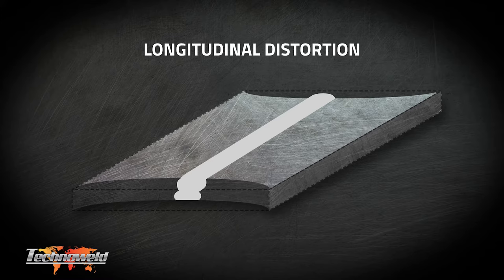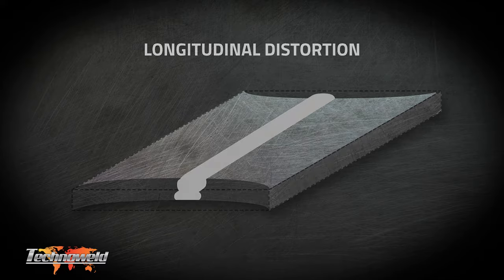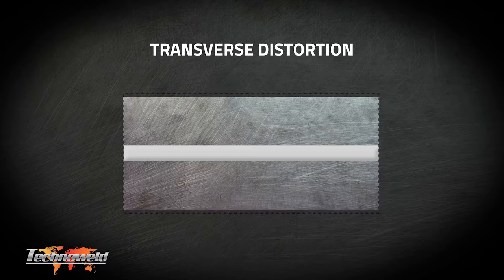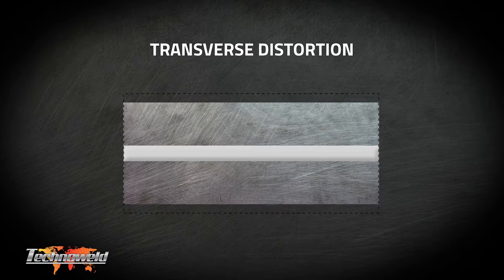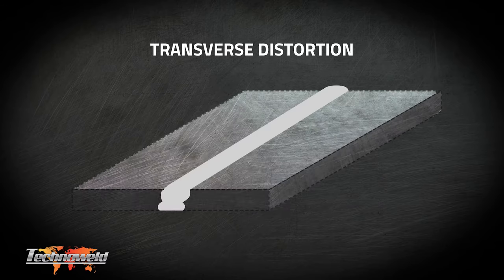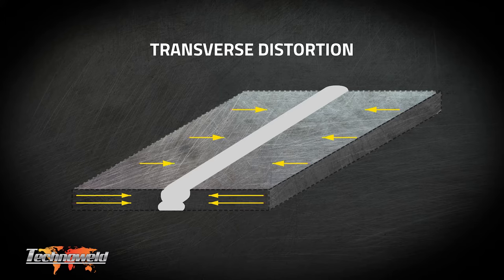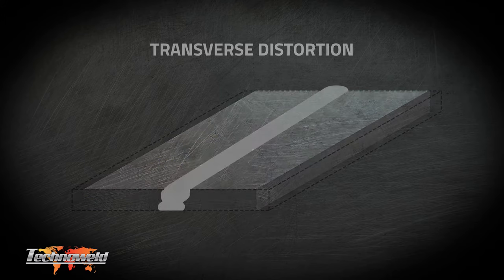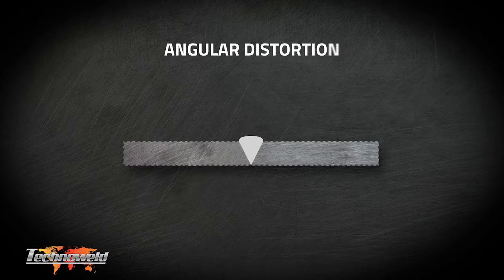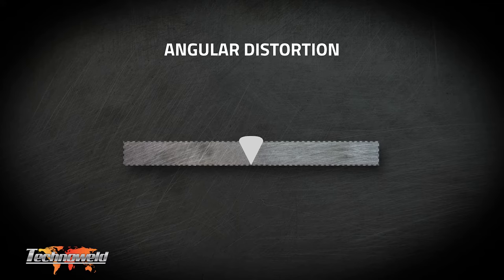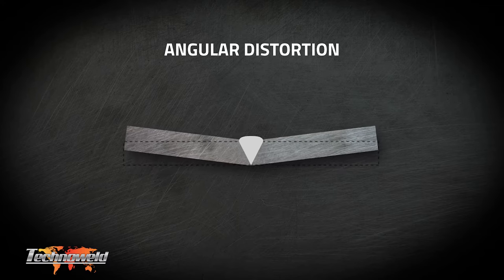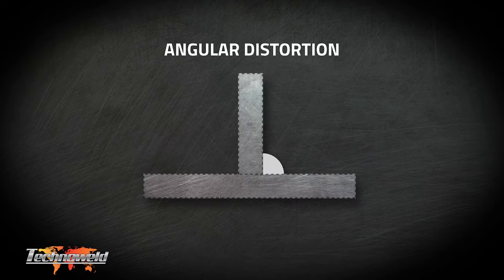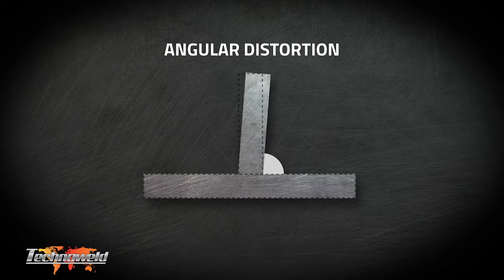Transverse distortion occurs when the metal contracts across the joint after welding and pulls the edges of the joint together. It is particularly obvious when there is a root gap between the plate or pipe. Angular distortion is where the angles between the welded parts are altered by contraction from the cooling weld. The contraction is greater where there is a larger weld as a large weld has more volume.